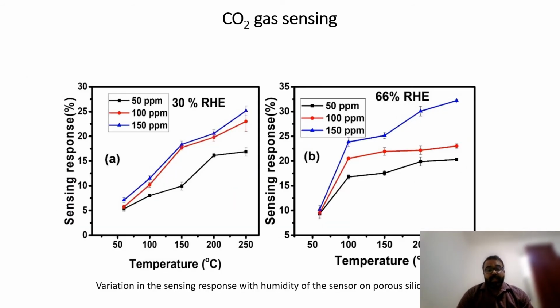Then we have studied the influence of humidity on the performance of the sensors, and we observed that with the increase in the humidity, there was a corresponding increase in the sensitivity. And the sensitivity increased to 32% at 250 and 150 ppm of carbon dioxide concentration. This may be due to the interaction of water molecules in the sensing mechanism.